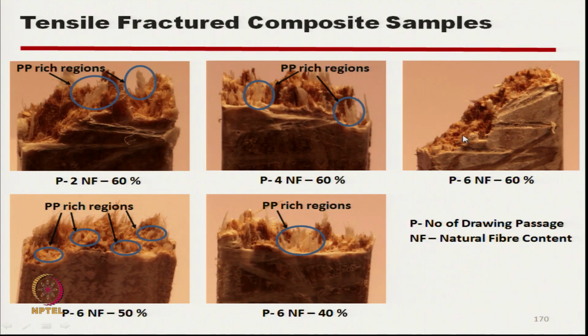So, these are the pictures of fractured composite samples. Here we can see, for say 60% natural fiber component, after fracture, this is a polypropylene rich region. Here we can see a polypropylene rich region, where the white patches are.